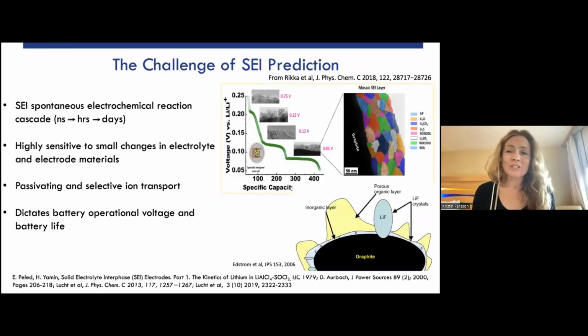And the challenge of understanding the SEI, I believe Kristina is one of the experts on this. She's done some really tremendously exciting work characterizing the SEI that I'm very grateful for, because this is something that we can compare to when we try to predict from first principles how it happens. This is a challenging area, because the SEI is a spontaneous electrochemical reaction that happens at the beginning of the first cycle, so nanoseconds, but then it keeps reacting over hours and even days of aging of the SEI.